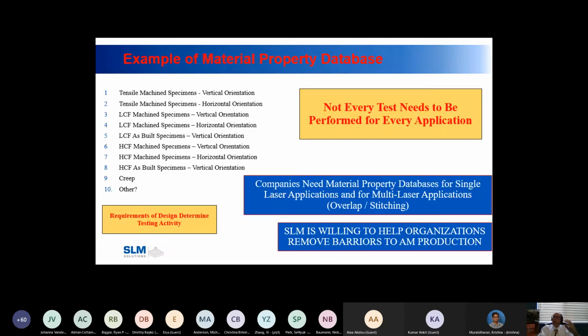All right. So how do we create a material database? It is the requirements of the component that dictate the tests that you do. So the tests that I am most familiar with are tensile, machine specimens, tensile machine specimens in the vertical orientation and in the horizontal orientation. So for an alloy like 718, you don't see that really, it's minute and sometimes not even at all. A variation in tensile properties related from vertical to horizontal.